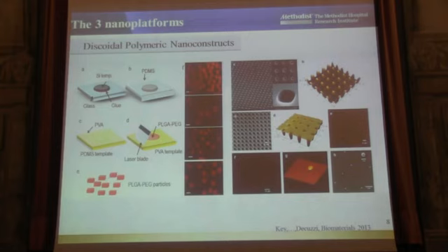1,000 nanometers by 1,000 nanometers. So these are conventionally considered very big by the nanomedicine community. Reviewers of papers as well as reviewers of grants say these are not nanoparticles, these are micron particles. Of course 1,000 nanometers, but it might be true. But they are 1,000 nanometers by 400, 500 nanometers in thickness. So they are submicron in size, I prefer to call them, and they can load a lot of things.